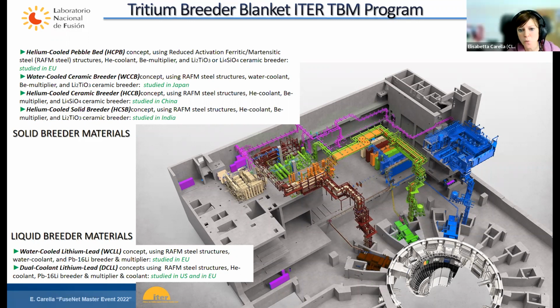in theory our loops work for DCLL conditions that work at higher temperature and higher velocities. So we need a facility able to work with these extreme conditions and check the corrosion, because the faster the lithium, the faster the corrosion. So we have to be able to observe how much time we can use our materials in this concept. So I think this is then a dedicated facility where you would appreciate the support of students. Probably you would like to have an internship there, or a master thesis project, I suppose, for master students.